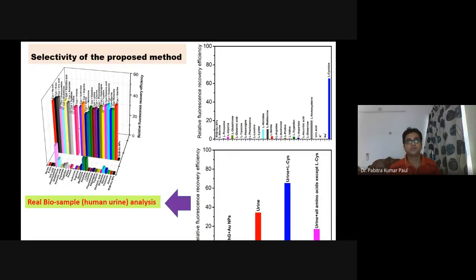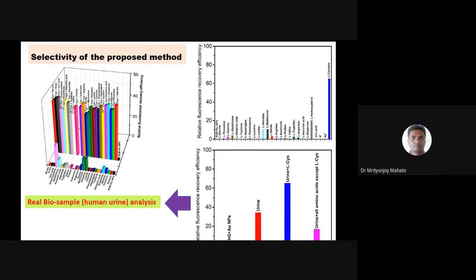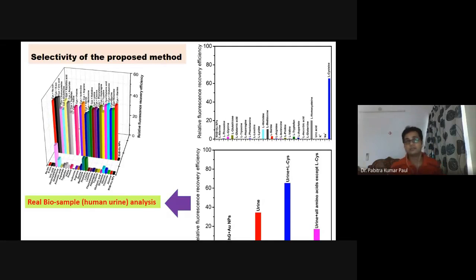So we can check various other essential and non-essential amino acids present in our blood plasma, and you can see here only, in case of, you can see the blue one here, the second top right corner, this curve. So this is L-Cysteine, and for all other amino acids there is no significant detectable signal compared to this one. And we can check the interference of the other essential and non-essential amino acids. And we also found a similar result, that presence of L-Cysteine gives the recovery of the signal. That's why it's L-Cysteine. So selectively it detects L-Cysteine.